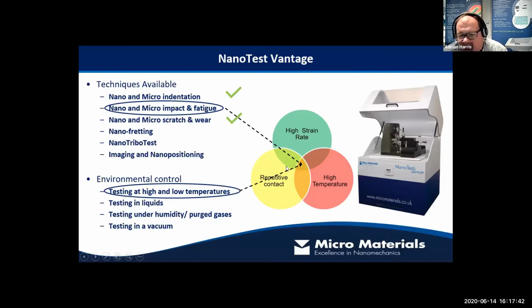So this gives us a really powerful toolkit. We can establish fundamental properties of the coatings themselves. We can look at how the adhesion of one coating compares to another with our scratch testing, and then we can do essentially what you might regard as an accelerated cutting tool type trial, cutting test type trial, with the combination of impact and high temperature.